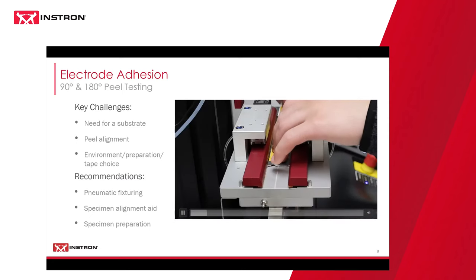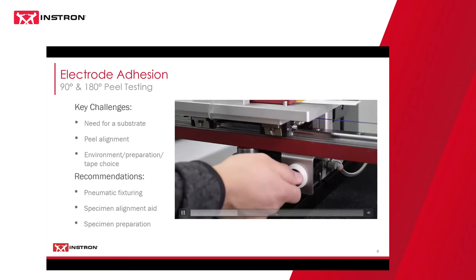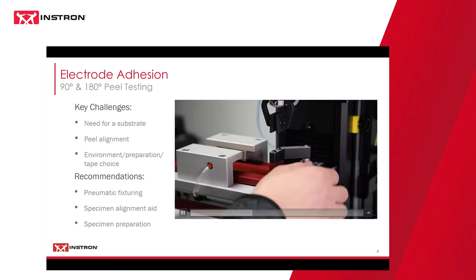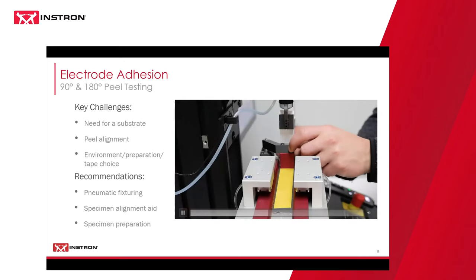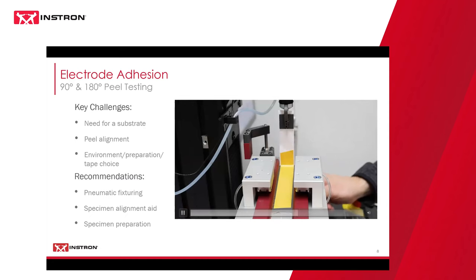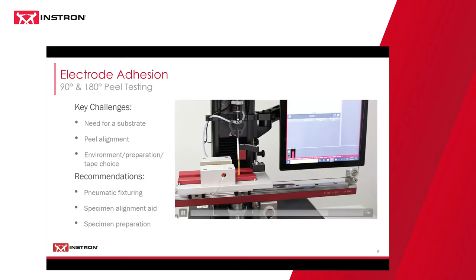So this is inserting the specimen into the clamps, and then a little flip switch brings in the swing clamp that helps you start your test in the same position every single time, lets you go to 90-degree alignment, and then you remove it and you can start your test.